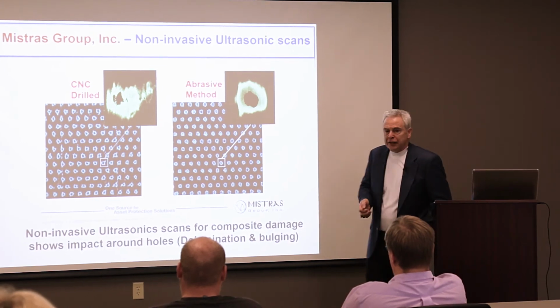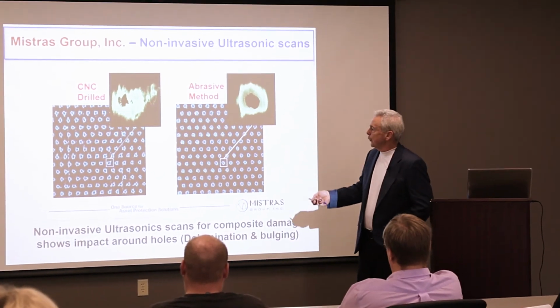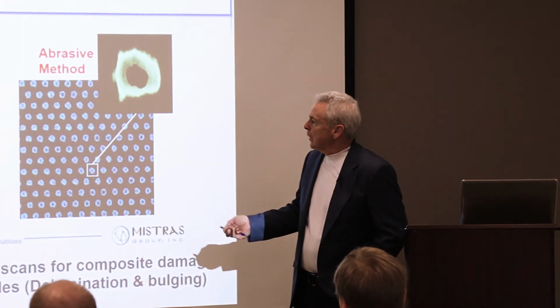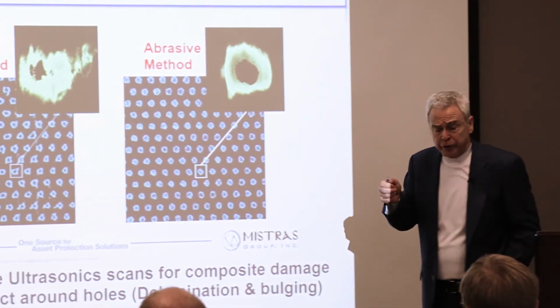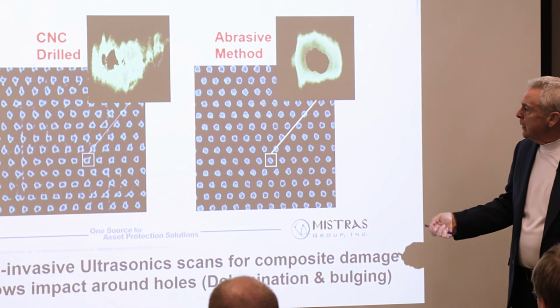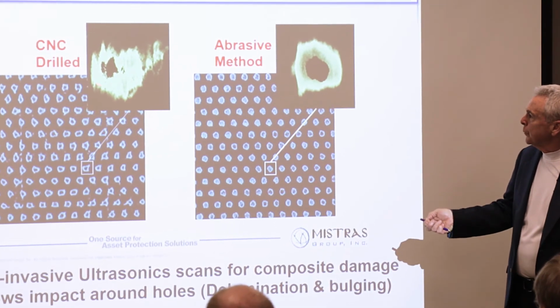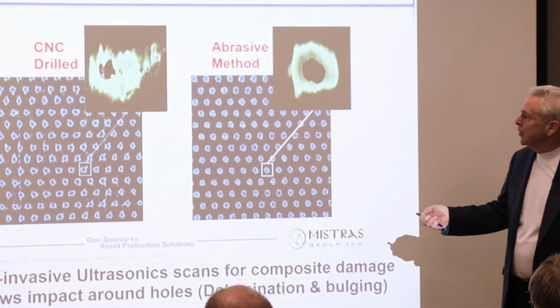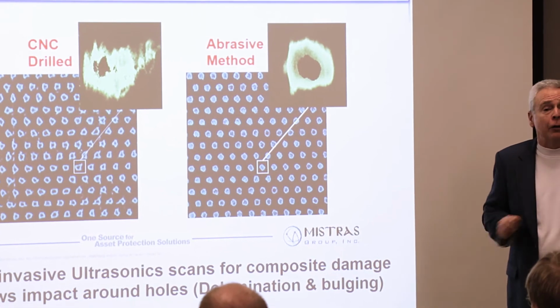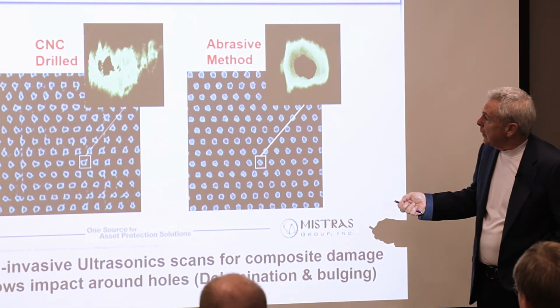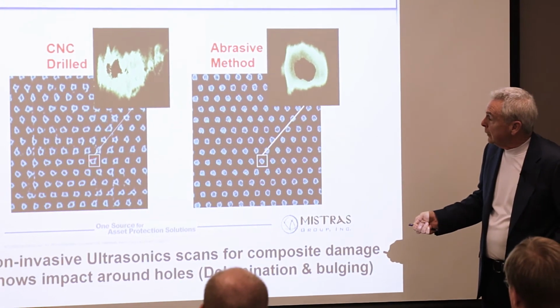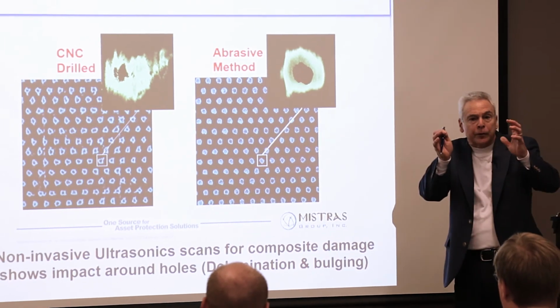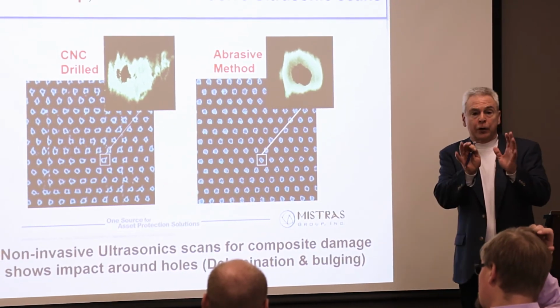What they did, they actually took a part that had been perforated and they did a non-invasive ultrasonic scan on it, and then they could do some micrographs and pictures to show what kind of stresses have occurred around each of the holes. And you can see, if you go around the periphery of the hole, that it kind of goes out from the hole. And that's what we were talking about before.